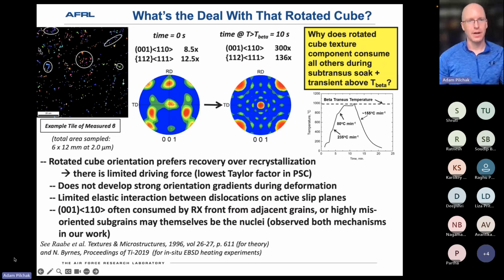So early on, I talked about the fact that at room temperature, when we look at the beta phase, we see this wide distribution of orientations, but for some reason, when we get right to the beta transus, you see only that single texture component with all of those subgrains. And to me, that was still the unanswered question: how you went from that initial state to that state right at the beta transus that then gives rise to all of the abnormal grain growth and everything that we're trying to avoid. So if you can fix that problem, then the abnormal grain problem doesn't come around at all.